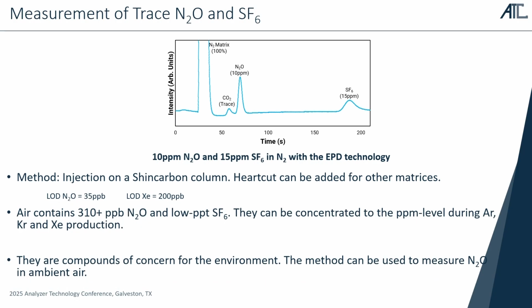Also, N2O and SF6 are contaminants that can be concentrated in the production of noble gases like krypton and xenon because they are at very low concentration in air, so you have to accumulate a lot of air to produce krypton and xenon. So you will also accumulate N2O and SF6. So it can be important to measure these compounds, and you can do that using argon as the carrier gas with limits of detection, again, at the ppb level.